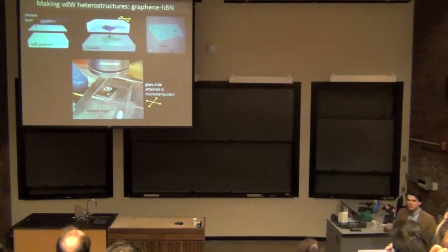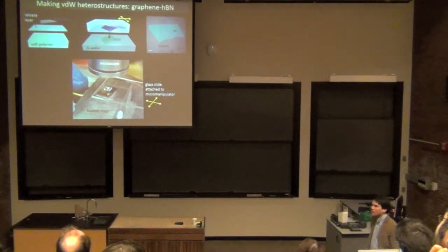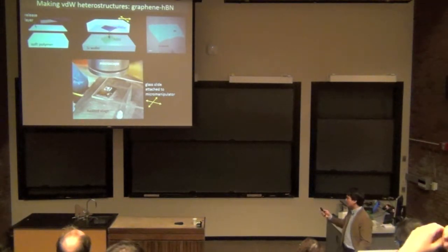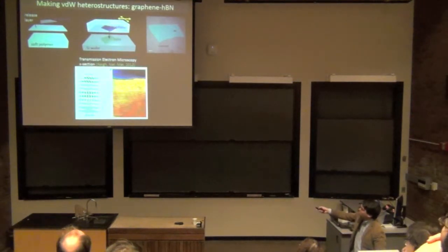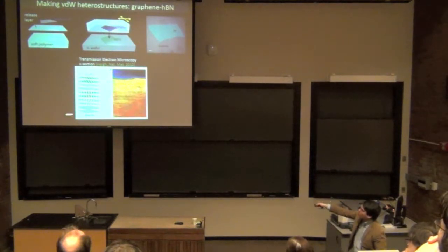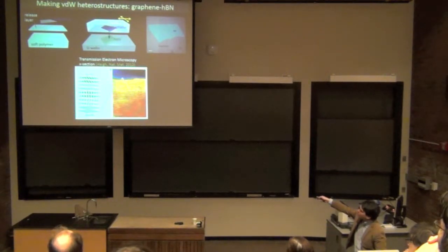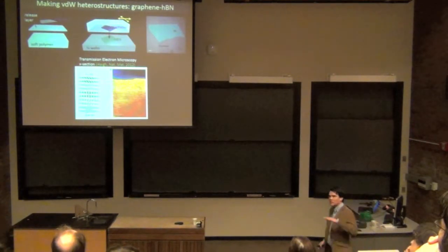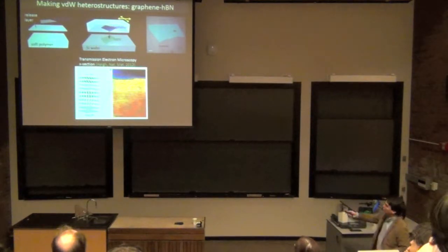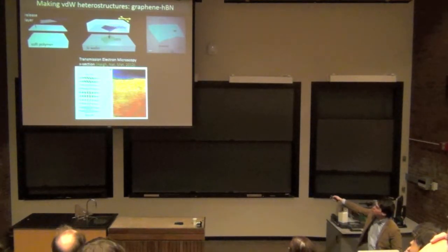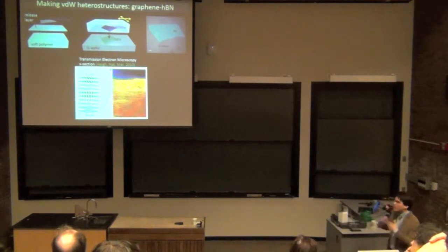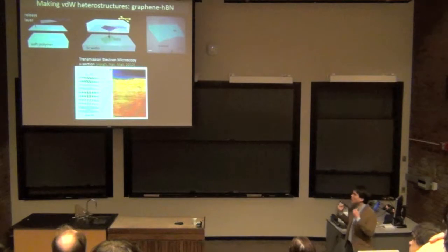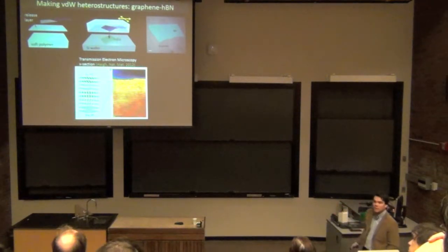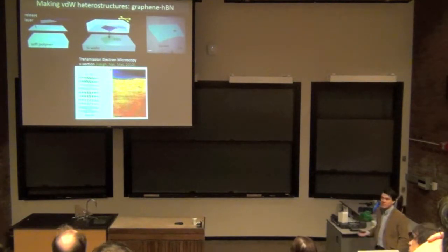And you know, this would be a nice kind of Friday evening type of experiment, except for one fact. And that fact is that when you actually look at a cross-section of a graphene boron nitride structure, this is now a stack of eight alternating bilayers. You see that the cross-sectional cut of this structure is perfectly atomically flat at the interface. Very few ripples, very few defects or anything. So we've gone from this Friday evening type of experiment into something that can make real high quality atomically flat interfaces between two materials that we basically just slap together.